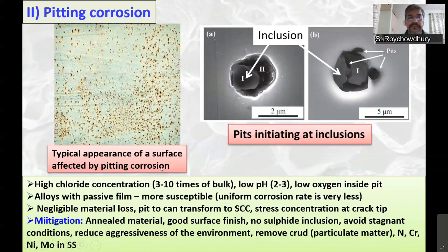Alloys with a passive film are more susceptible. The uniform corrosion rate is less, as I told before, so material loss is actually negligible. If you measure the weight change, it will be immeasurable. However, it can lead to a hole or pit which breaches the entire wall thickness, and at times, if it is under load, you can have stress concentration at the tip of the pit.